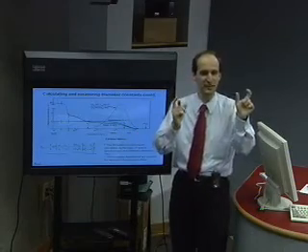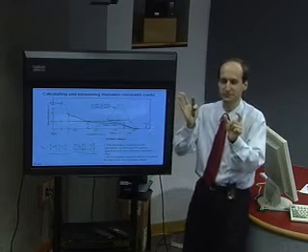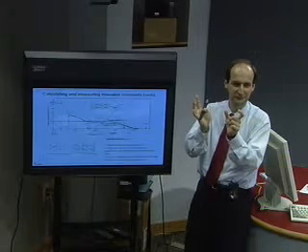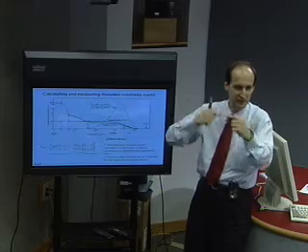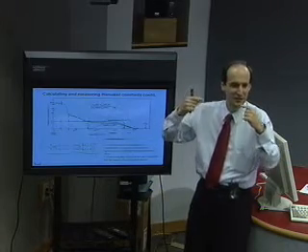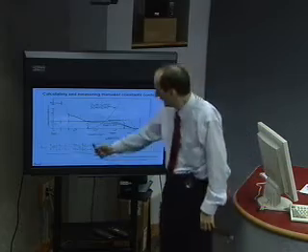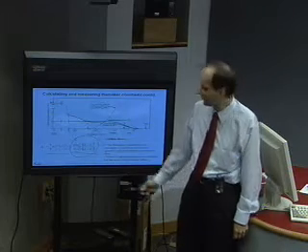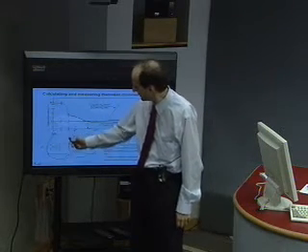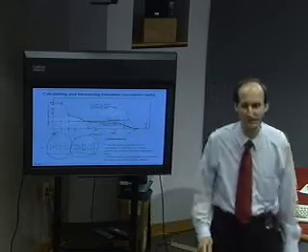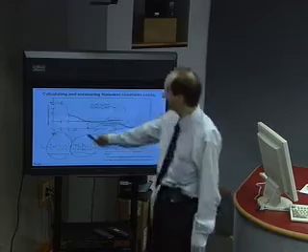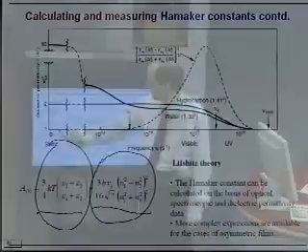Physically, when you have dipoles, you always have polarizability at any frequency. Even if you apply a constant field, the dipole would orient itself and polarize. When you have van der Waals forces, you have the electrons moving at high frequencies. So the purely dispersive London interactions are the ones which are expressed by the refractive index. All other types of ionic and dipolar interactions are the ones which are expressed by the polarizability. And then you have this complex frequency chart where you have the permittivity as a function of frequency.